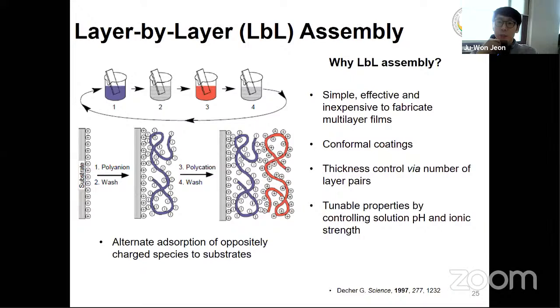And the second approach we use is the layer by layer assembly. Layer by layer assembly is a very simple, effective, and inexpensive method to fabricate multilayer films. If you have a charged substrate, you can immerse it into a solution which contains oppositely charged species, like negatively charged species. This species can be a polymer or metal oxide or anything. Then there will be charge attraction, and this negatively charged species can be adsorbed onto the positively charged substrate. And then you can immerse it into another solution which contains positively charged species, and then there will be another adsorption process.